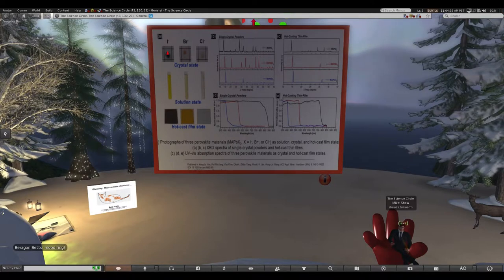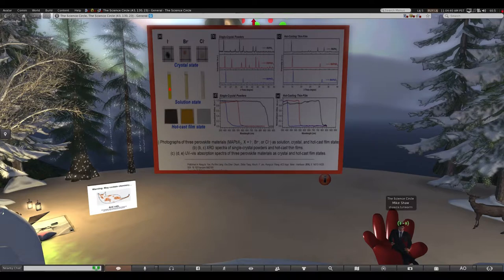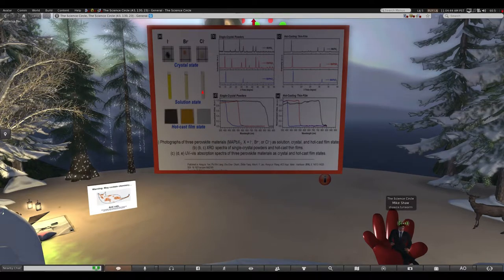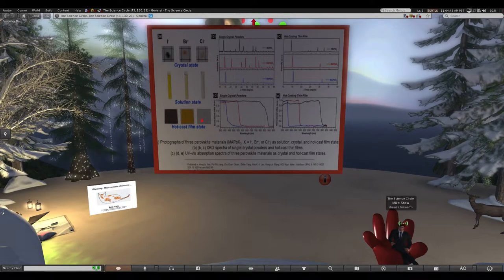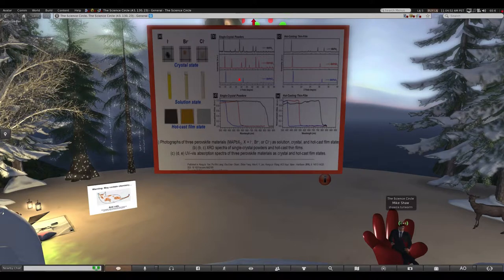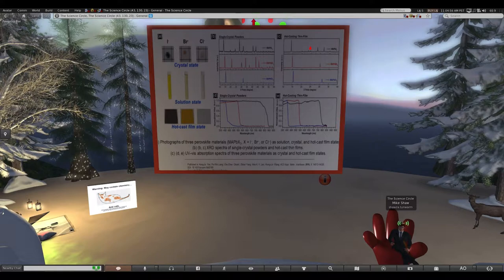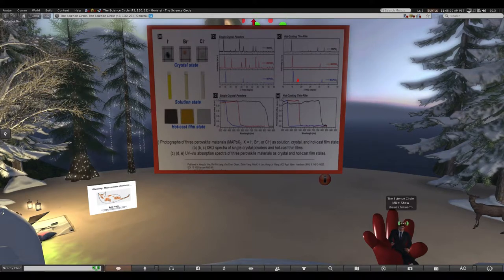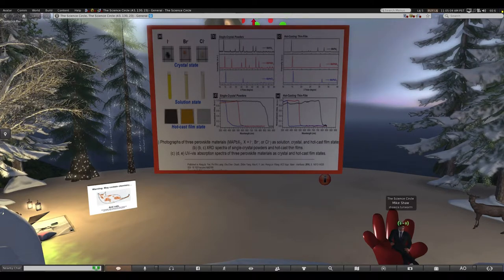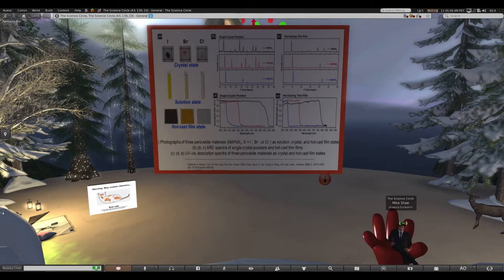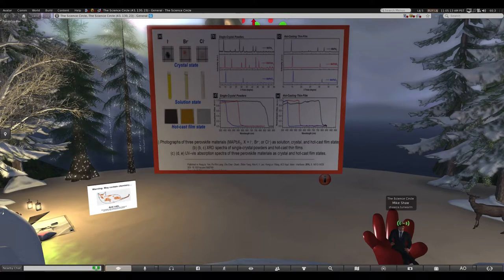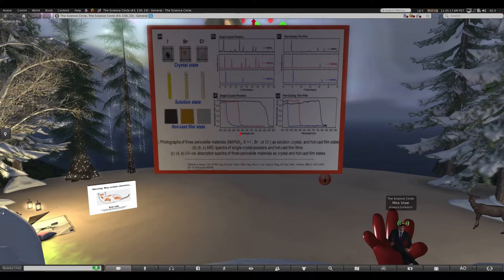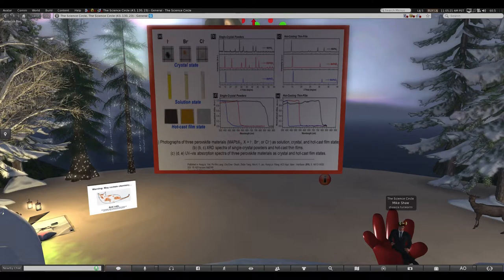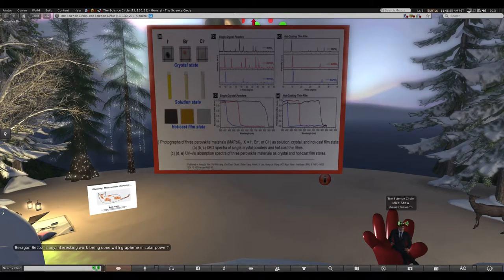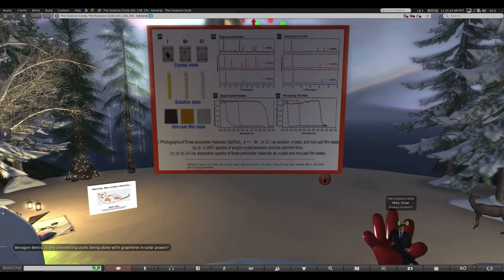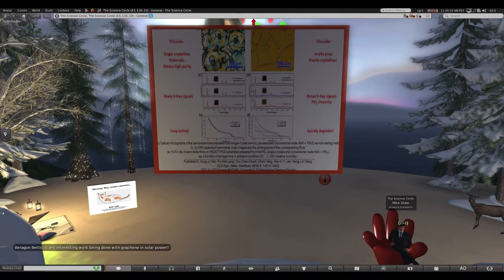Basically they took various compounds. You can see crystalline. They take their crystalline pure materials, dissolve them up, and cast them and make films out of them. And essentially, you can see the single crystal powders have some nice X-ray bands, nice and sharp. After you make a thin plate of them, still nice sharp bands. Some of the weaker intensity bands aren't seen anymore. That might just be a thickness issue. And then these bottom pictures are basically absorbance versus wavelength, so it's showing you which wavelengths these things will absorb. The black one, I think it's the iodide one, seems to be the one that gets most of the visible light. How do these things compare with what people are usually doing?